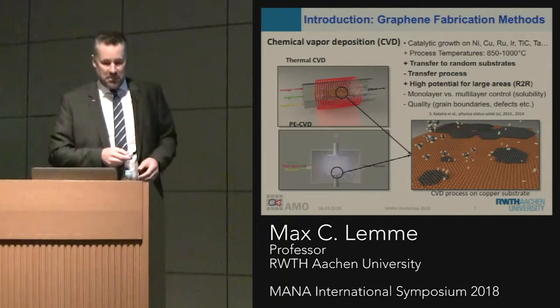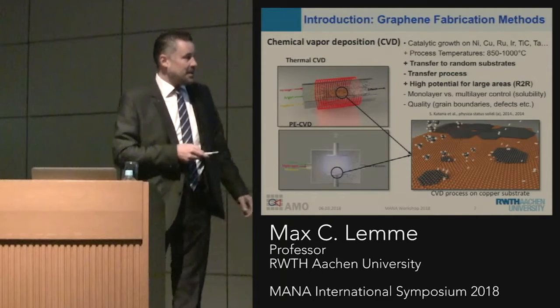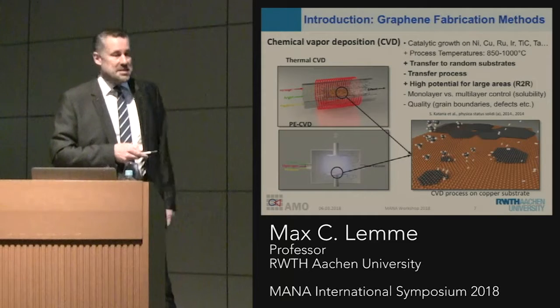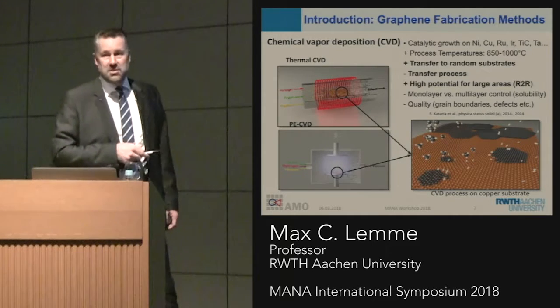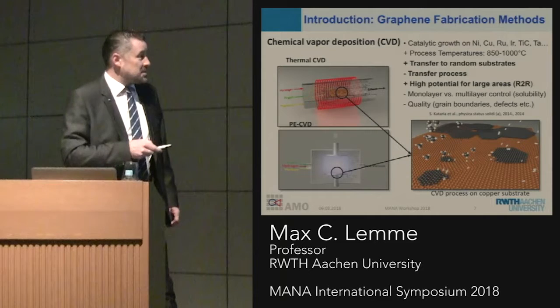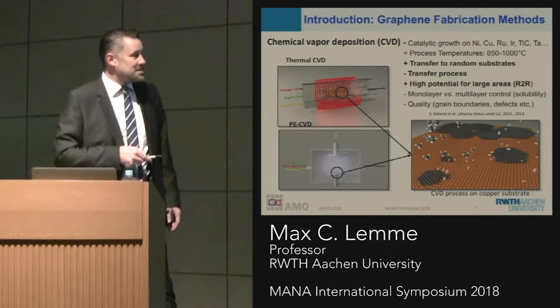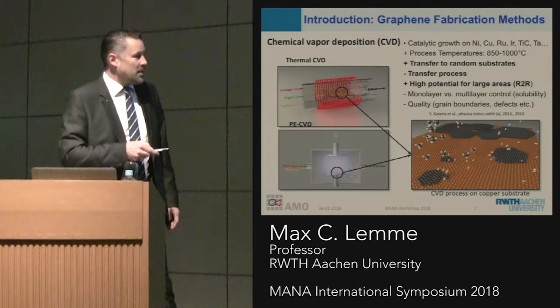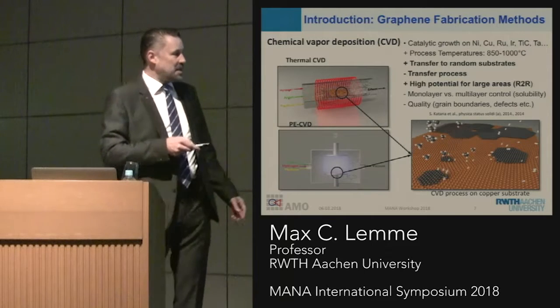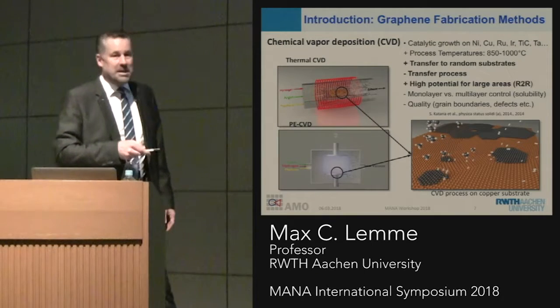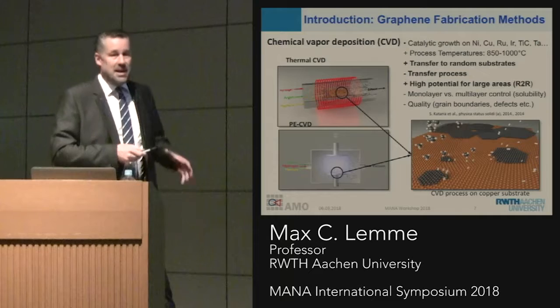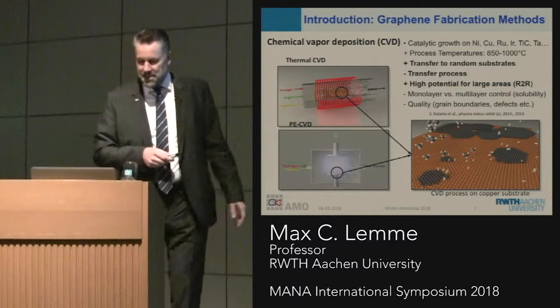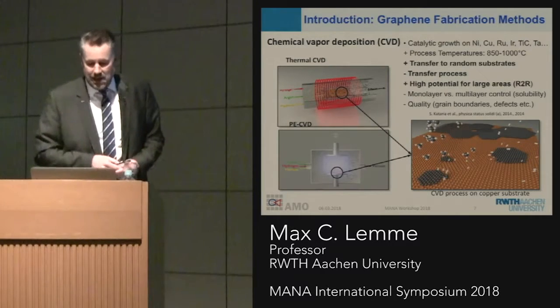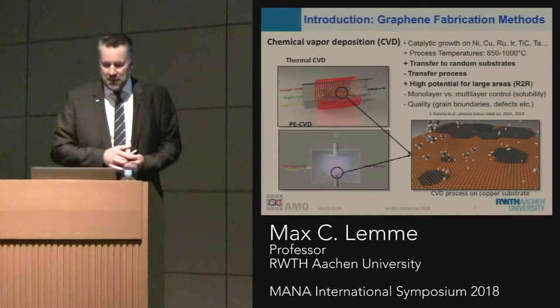Here's the example of graphene, where we typically take a metallic surface, a catalytic surface. In our case, we use copper, and we use thermal CVD or plasma-enhanced CVD methods to grow, from a gas phase, from methane in this case, monoatomic graphene layers on the surface, and then we transfer them. This has the advantage that it's large scale, and we can do this on a wafer scale even.